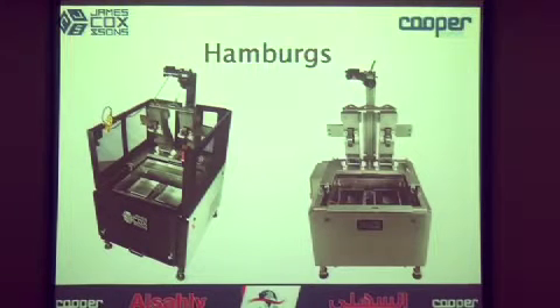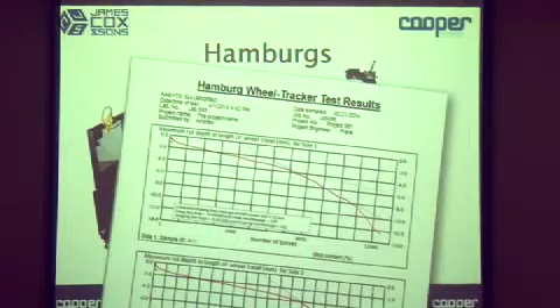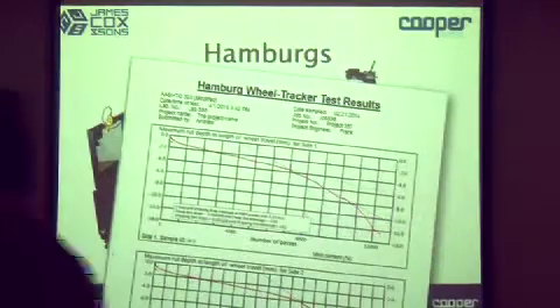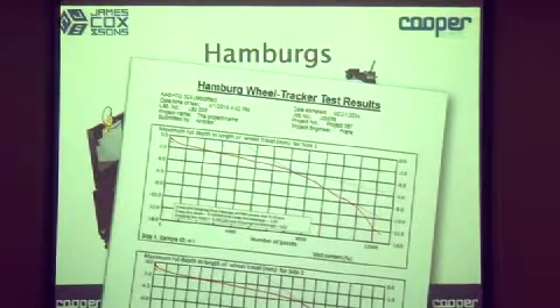Now in California, the only machine the California Department of Transport will purchase is stainless steel, and also we've worked very hard with them to produce a way of interpreting the slope and the stripping slope. That's that all-important selection. We're the only people with an automated way of analysing the data from the test and telling you whether you have a stripping inflection point, or whether the material never reached that stripping point at all.